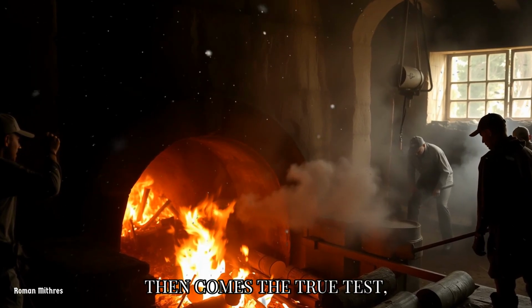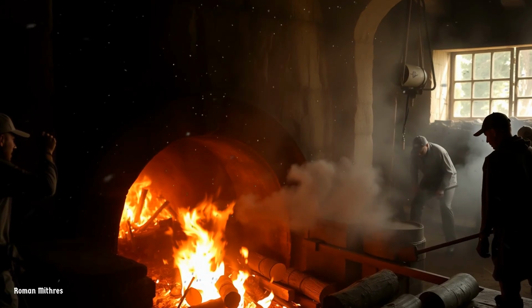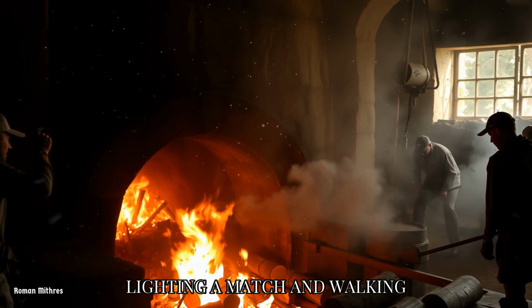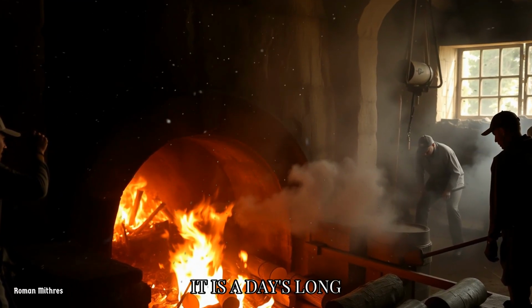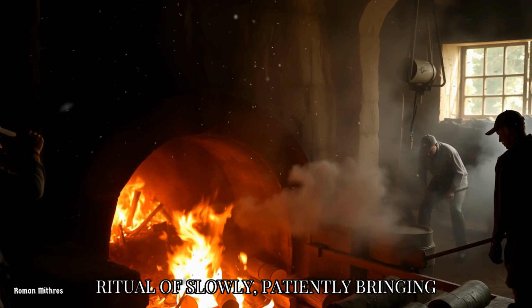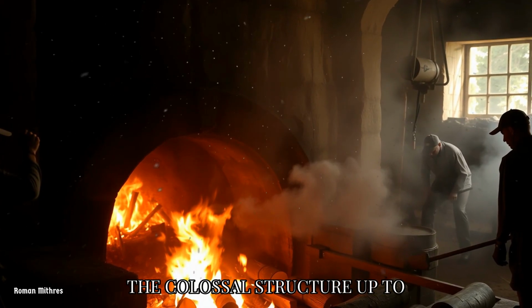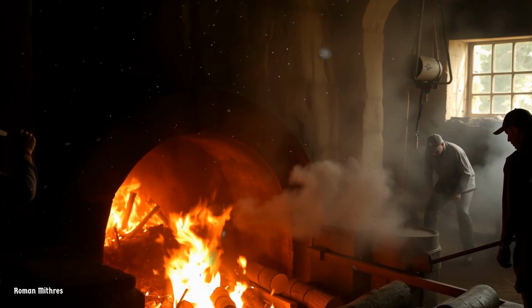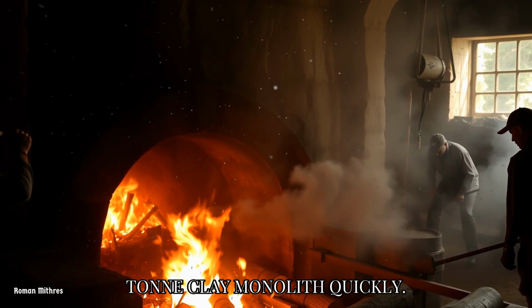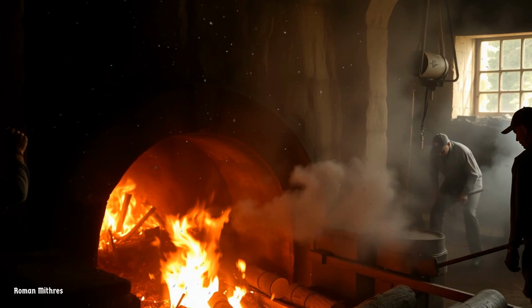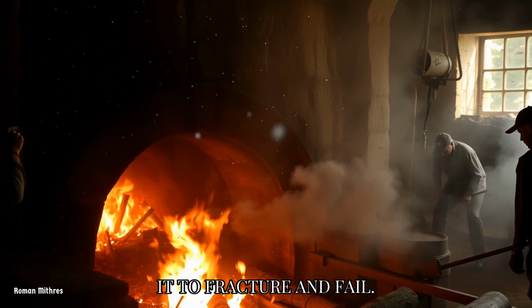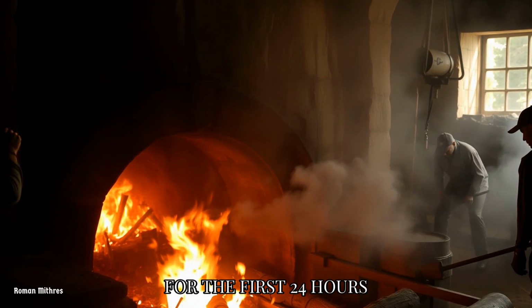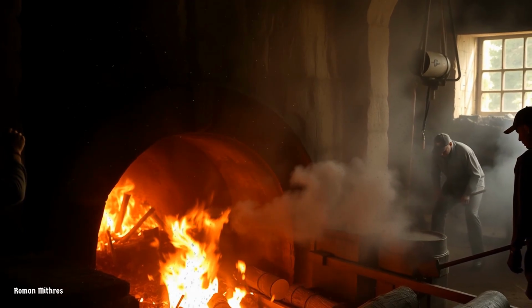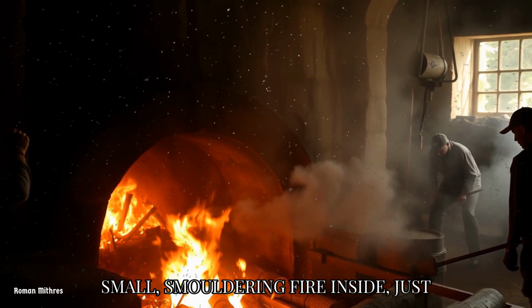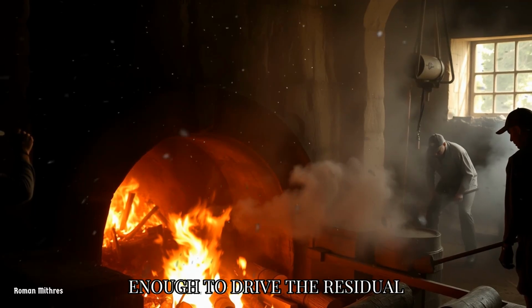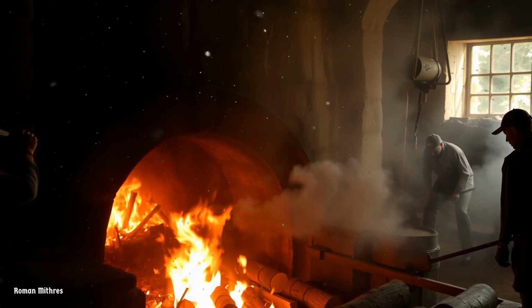Then comes the true test, the first firing. This isn't a matter of lighting a match and walking away. It is a days-long ritual of slowly, patiently bringing the colossal structure up to temperature. You cannot heat a several-ton clay monolith quickly. The thermal shock would cause it to fracture and fail. For the first 24 hours, they might only have a small, smoldering fire inside, just enough to drive the residual moisture out of the clay walls.